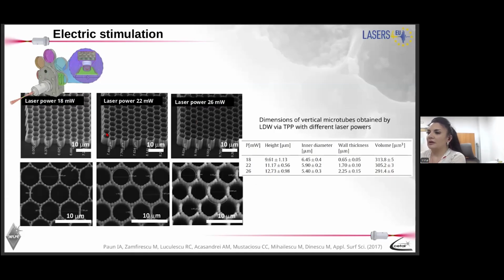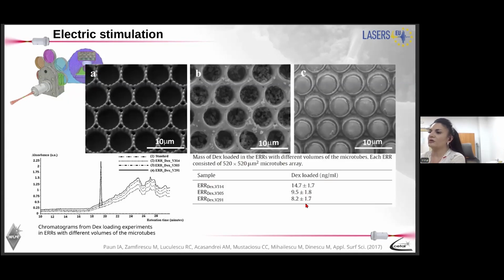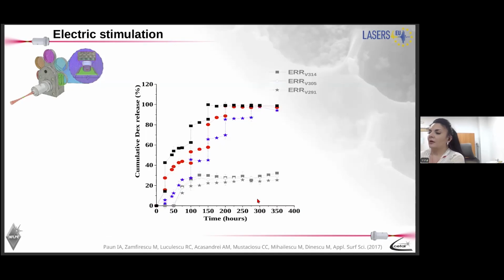These are our structures seen in scanning electron micrographs, and their dimensions along with their volume. The volume is important related to the amount of drug that can be loaded into each of these microreservoirs. You can see here a nice top view image with the microreservoirs empty, then partially filled with polypyrrole and dexamethasone, and then coated with a PLGA layer. The most important result here is that in gray is the passive drug release, and in color you can see a step-like behavior of the drug release, according to the green arrows that correspond to the applied electrical stimuli on these samples.